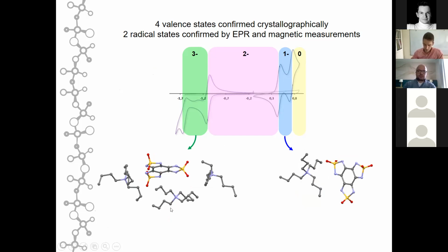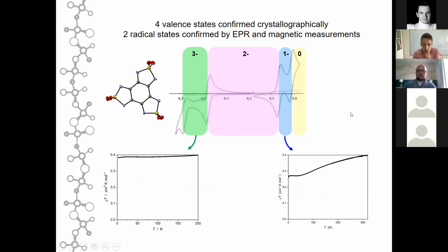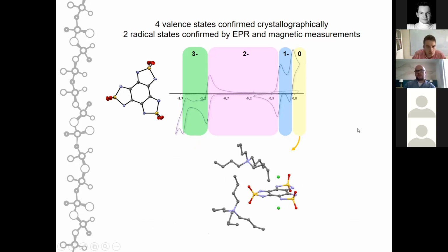So we also obtained the crystal structures for this compound. So these states are characterized structurally. And we also recorded the magnetic properties. In the case of the trianion, the properties are as expected for an isotropic spin 1/2 system. In the case of the monoanion, there's something very strange happening. And this is even stranger in view of the fact that there are no pi stacking interactions for this molecule. The spin 1/2 molecules in the crystal structure that I was talking about are well separated from each other. So we don't understand why there is this kind of decrease of the magnetic moment for this system.